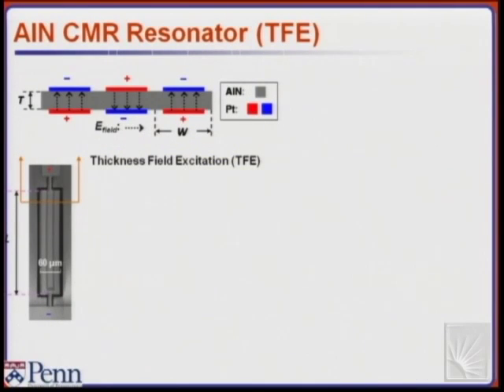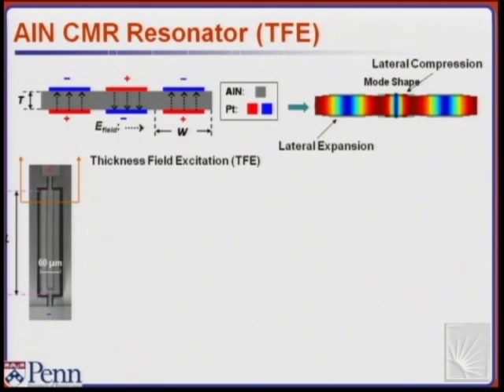So how the device exactly works, this is an SEM picture showing the device. This is what we call a 3-finger device, in which we basically apply a vertical electric field across the film thickness. And you can see how we switch the polarity of that electric field so that we can basically induce lateral expansion and contraction in the adjacent element. So you can see it as an individual element that is mechanically coupled to the next one, or you could see it as an overtone of a plate. Either way will work as long as you use a 1D model.